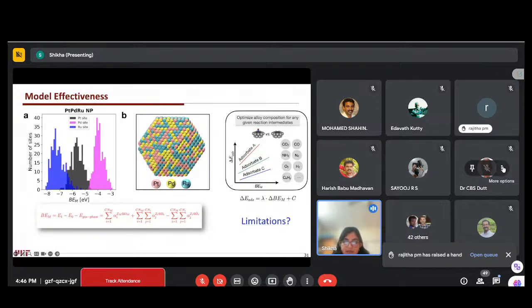Now further, what is the limitation of our model? Right now the limitation is that the metal atoms we are picking should have very close lattice parameters. If the difference in the lattice parameters of the atoms is large, then there would be a lot of strain within the system, and we could see bonds breaking, maybe on the surface of the nanoparticle, or the particle may not be stable. Having a lot of strain in the system will induce a lot of error in the model. Therefore, for strained systems, we need to further improve the model.